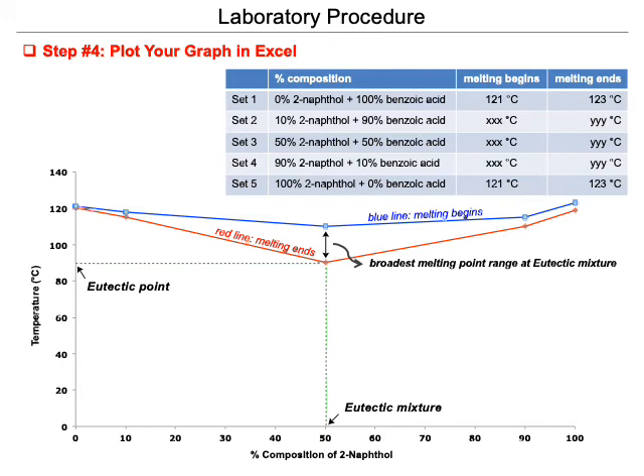At the end of our experiment, we can draw this blue and red line, as you see. We have the 10% mixture, the 50-50% mixture, and the 90-10% mixture. As I mentioned, 0 for one of them is 100 for the other one. When we have 100 here, it means the other one is 0. So both ends of this curve are pure materials. Here is the pure 2-naphthol, for example, and here is the pure benzoic acid, and these are the second point, the third point, and the fourth. And you see that the broadest melting point depression is at the eutectic conditions.